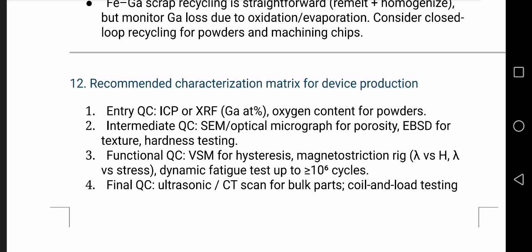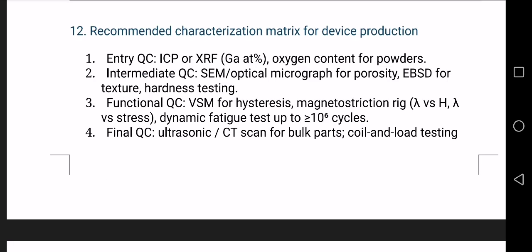Oxygen content, especially for powders. Oxygen increases brittleness. Oxygen reduces magnetic response. Therefore, oxygen analysis is mandatory for powders.